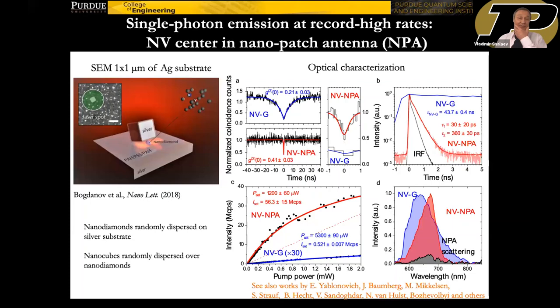Here, I'm showing our first simple-minded experiment done some time ago. We would simply take nanodiamonds, relatively small in size, like 25 nanometers, so that some of them have a single nitrogen vacancy, and just randomly distribute them on a silver film. And then randomly disperse silver cubes, so that just by chance, in some cases, a silver cube would end up sitting on top of a nanodiamond. Of course, it's not really a deterministic approach, but still we obtain that typically on average, we would get like 100 times increase in the rate with which single photons are emitted, and also the brightness of the source was increased roughly by 100, meaning that it was all radiative. And to prove that we are dealing with single photon sources, as always, we would measure this G2 correlation function. But this approach, of course, is far from being optimal.